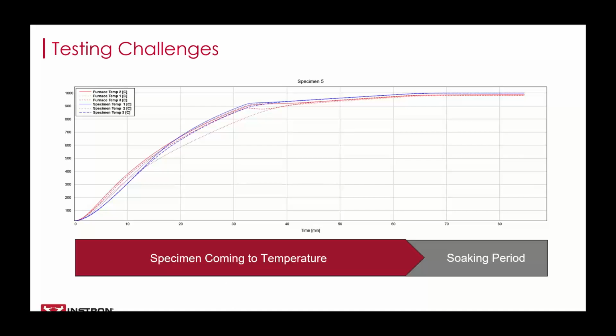at that temperature for a set amount of time to ensure that entire specimen has reached equilibrium in its environment. We have a visual on the screen that shows you some heat up tests that we ran in the lab up to 1,000 degrees Celsius. The temperature of both the furnace and the specimen were tracked during these tests. The red bar below the graph shows how long it took the specimen to come up to temperature. This will vary depending on the material type you're testing. You can see it takes a considerable amount of the overall test time. So if your lab is trying to complete multiples of these tests a day, you can see how this test duration quickly eats away at throughput. Next slide, please.